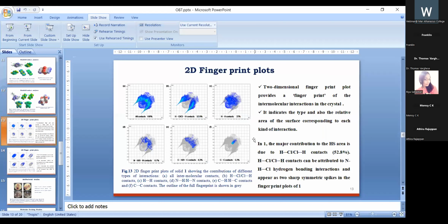Another important piece of information obtained from the Hirshfeld surface analysis is the two-dimensional fingerprint plots. It provides a fingerprint of the intermolecular interactions in the crystal, and it gives information on the type of interaction and also the relative area of the surface corresponding to each kind of interaction. Figure 13 represents the fingerprint plots of 1, and in 1, the major contribution to the Hirshfeld surface is due to H...Cl interactions, contributing about 52.8% to the total surface, and that appears as two sharp symmetric spikes.